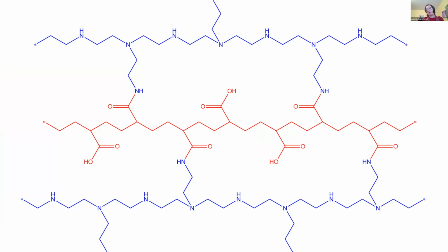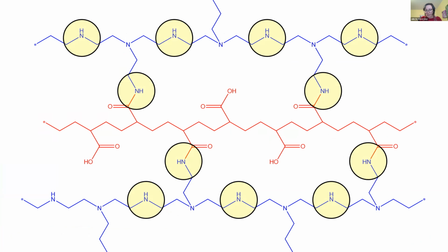So here's an example of a polymer coating chemistry. If you zoom way in to look at its chemical structure, you might see something like this. And what's key here are these particular functional groups. These functional groups are capable of being chlorinated using the concentration of chlorine that's commonly used in sanitization of food contact and non-contact materials, 200 parts per million bleach, right? And then they can become antimicrobial halamines, like what's highlighted here.